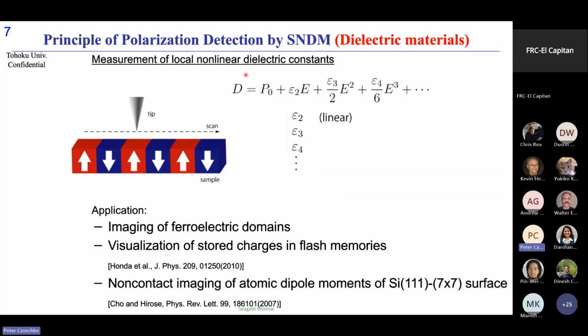Anyway, here I'd like to explain how to detect the polarization by using SNDM. This is a polynomial expansion form of the electric displacement as a function of the electric field, or stored charge or applied voltage. P0 means the spontaneous polarization of the ferroelectric material. Epsilon 2 is the linear dielectric constant. Epsilon 3 is the lowest order nonlinear dielectric constant. And epsilon 4 is a higher order nonlinear dielectric constant. And this number means the rank of the tensor. Anyway, an even rank tensor, including the linear dielectric constant,